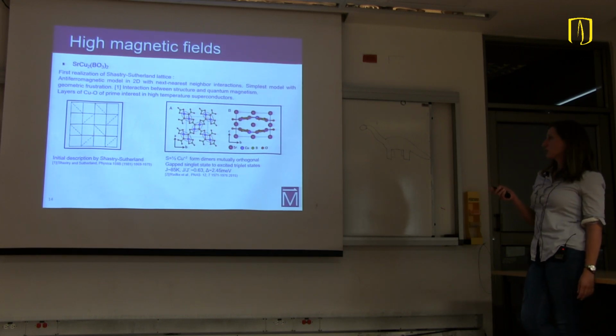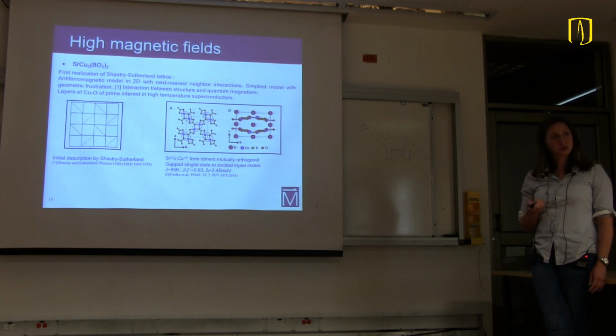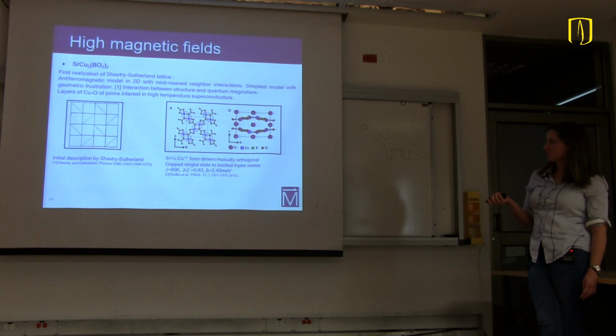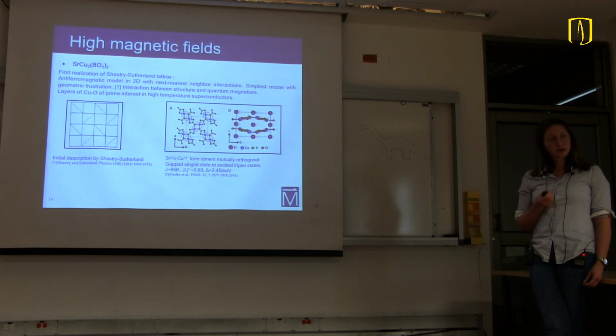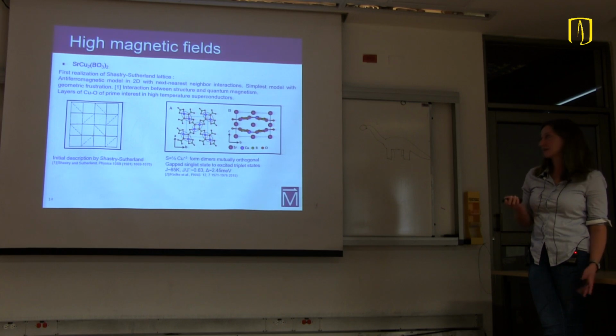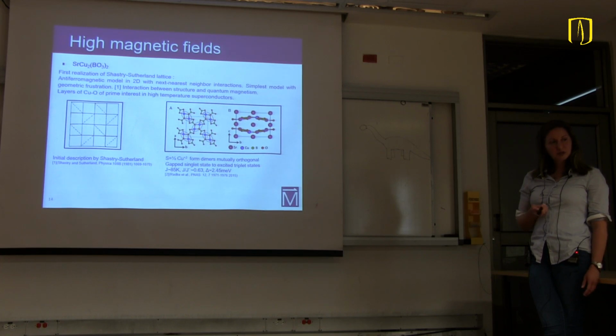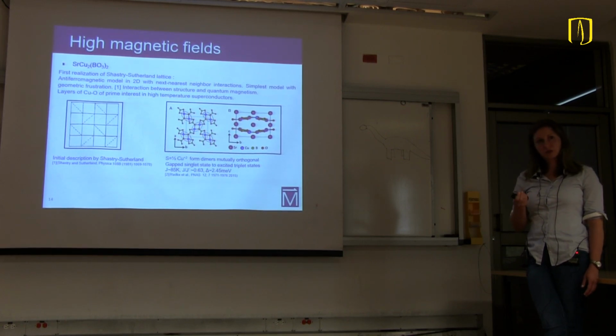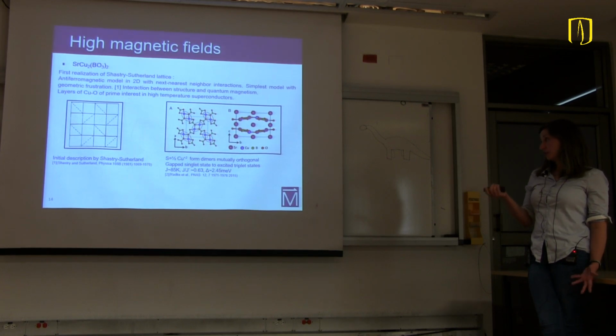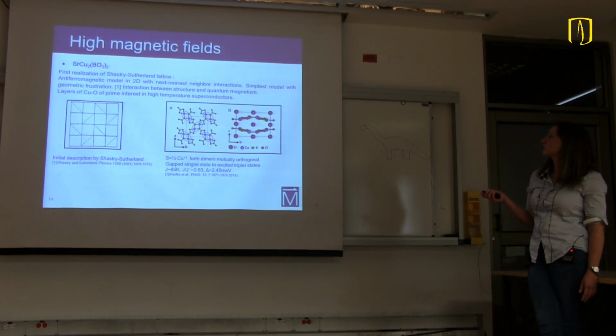So there was one model developed by Shastry and Sutherland in the 70s, 80s. So it's a theoretical model of an antiferromagnet, a frustrated magnet. That's the lattice. And what's really interesting is that it was first a theoretical model to play with frustrated magnets. But recently, one compound, called SCBO, was found to be the first experimental realization of this theoretical model. So physicists got really excited because they could finally test this theoretical model in real experimental conditions.